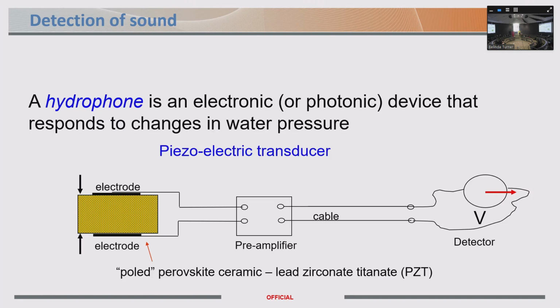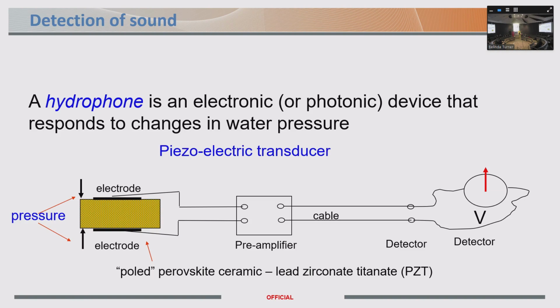So the basic technology that underpins all of undersea acoustic sensing is what's called a hydrophone. So a hydrophone is just basically an underwater microphone, essentially. It's basically a device, usually an electrical device or electronic device, that responds to changes in water pressure. And so almost all hydrophones since the 1960s have been based on the piezoelectric effect. And so the piezoelectric effect is very simple. You take a material which is piezoelectric, and you apply pressure to that material, and the material has this interesting property that when it's deformed, it actually generates a charge, and you can detect that on a detector. So that's how piezoelectric hydrophones work.